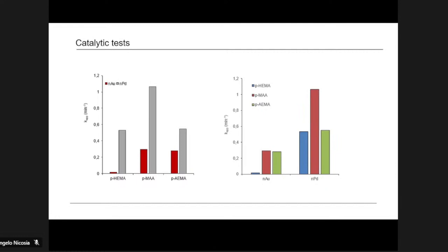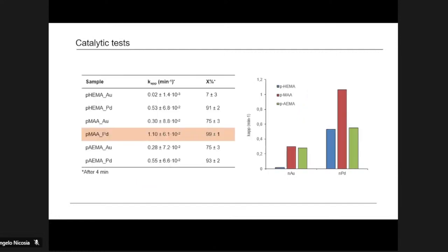But the most peculiar system was observed when we compared the type of the polymers that we used to immobilize our nanoparticles. In particular, we can follow the slide and the system with methacrylic acid. The methacrylic acid moieties represent the most active system. Why? That is our first question.